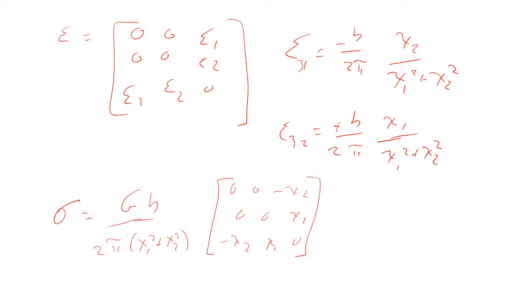The stress field around an edge dislocation is quite a bit more complex because your displacement field depends on a lot more things, right? Your displacement field is going to depend on the width of your dislocation core, which is going to depend on the properties in the planes, right? So in order to get the stress field for an edge dislocation, you have to go a little deeper into classical elasticity theory. The most straightforward way is basically to think about it in terms of the Airy stress function, and you can work it out. But that's a little too beyond the scope of, I think, what we need. So we just give the stress field for an edge without commenting on it, right?